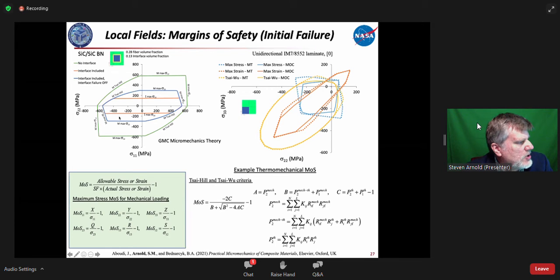Here, the blue shows what happens when you do include an interface, and yet you're not allowing it to actually fail. So obviously, because of the compliancy, it's providing you a smaller surface. But when you allow the interface to then fail, you're getting a very sharp failure along that transverse direction. And it's significantly underneath. But one of the nice things here is you can see the different failure criterions in the different domains, and also we can pick up with micromechanics, obviously, because we have access to local fields, which phase is actually failing. Here it's the matrix, here would be the interface.